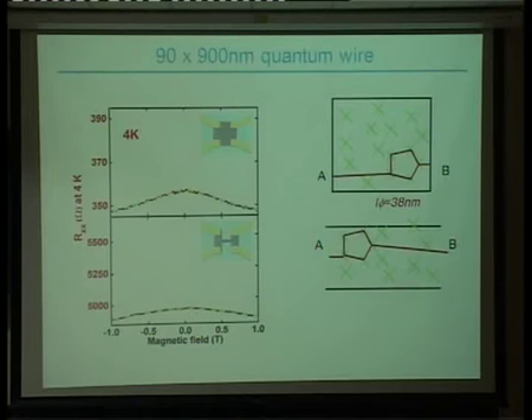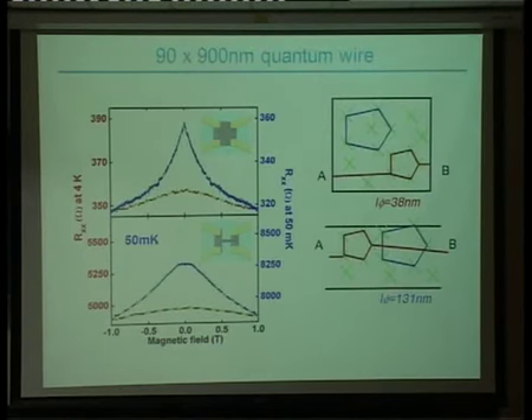And if you fit this to the Hikami formula for disordered conduction, you can extract the phase coherence length of about 38 nanometers. So you can see whether you're in this square structure or this wire structure, you form these phase coherent loops very nicely. If you now cool it down to millikelvin temperature, you can see the difference between the 2 devices. You see as you reduce the phonon scattering, the resistance goes up. You form larger and larger of these phase coherence loops and the resistivity increases. And as you apply the perpendicular field, you break the phase coherent backscattering. If you now fit this, you see that the phase coherence length is about 131 nanometers, which is easy to form in these square structures.